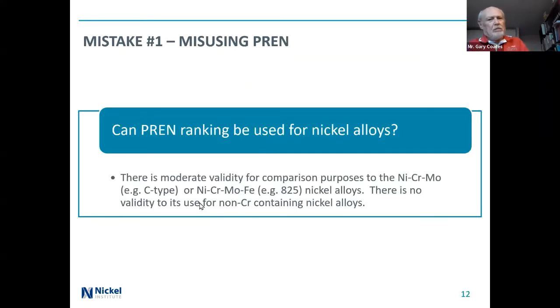Can PREN ranking be used for nickel alloys? Well, there is some moderate validity for comparison purposes to the nickel chrome moly nickel alloys, such as the C-type, C276, C22, alloy 59, etc., and the nickel chrome moly iron alloys, the ones that have a higher iron content, such as 825. It's not exact, it's not as good as it is for stainless steels, but it's not bad. It gives you an indication.